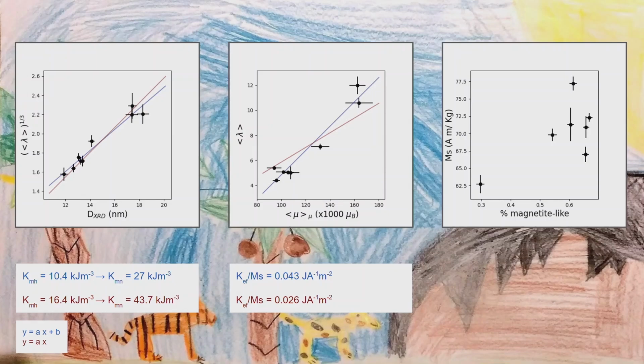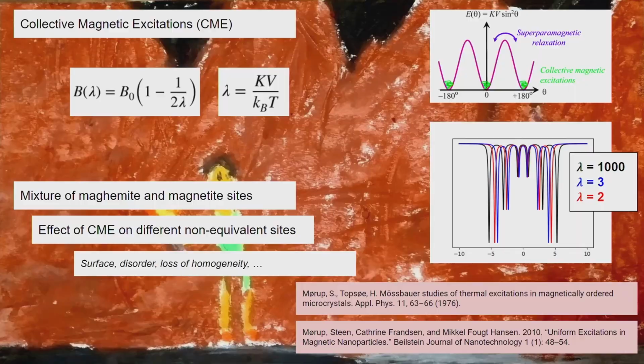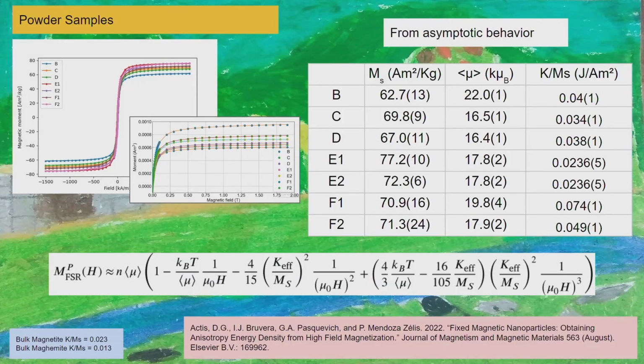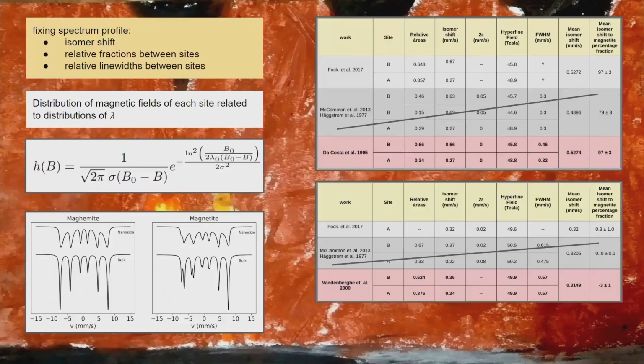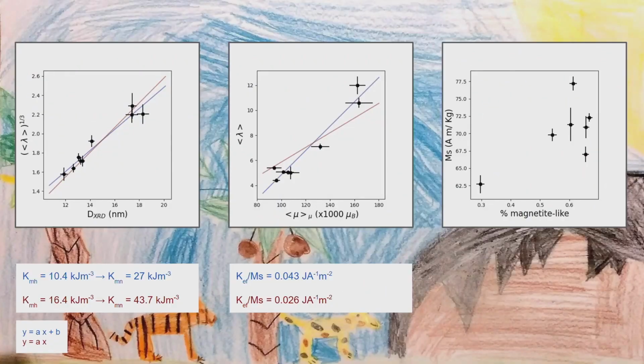And from lambda versus mu, we can obtain from the slopes the relation of K versus MS, magnetic saturation, that is also near the values of literature, or the bulk value. When we made this study, we obtained from 0.4 up to, this is strange, I suppose we have to remove it, but all the other ones are between 0.02 and 0.4, and here are the values for bulk, 0.023 and 0.013. So the mean value obtained from the correlation is also very good.